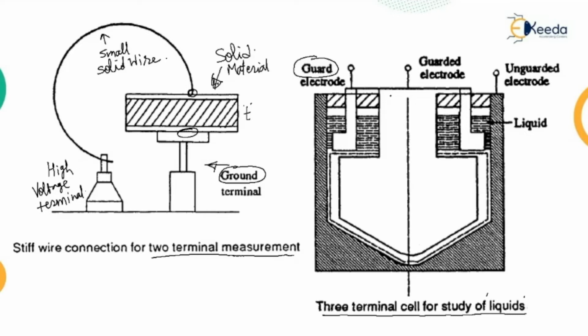The opposing surfaces of the measuring electrode should be carefully finished to give a polished surface and a uniform spacing of about 0.25 mm. That spacing must be 0.25 millimeter, and that is to be maintained. The insulation should be able to maintain the alignment of the electrode even at the highest temperatures used, and should still allow easy disassembling and cleaning. So this is one kind of three-terminal cell for study of liquids, where we have a guarded electrode and an unguarded electrode, and here the liquid which is to be tested is placed.